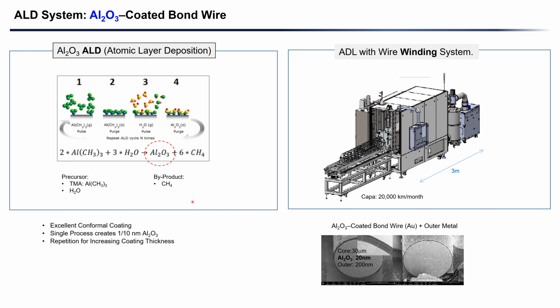On your right-hand side, you're seeing a special chamber for coating aluminum oxide on a bond wire. This is the chamber for the ALD process. You're seeing a special spool for coating aluminum oxide on the wire. When a wire winding is finished, this whole thing is moved into the chamber for the ALD deposition.